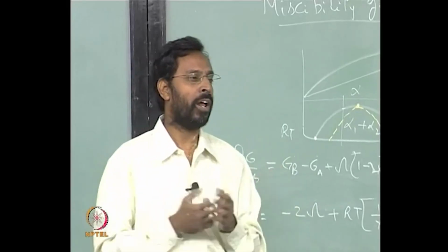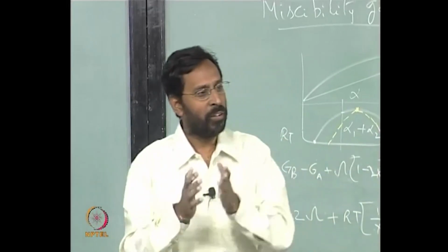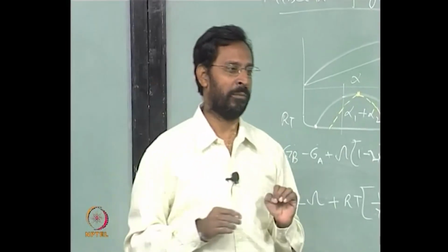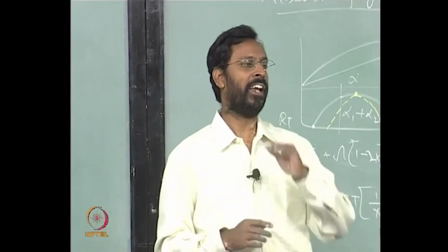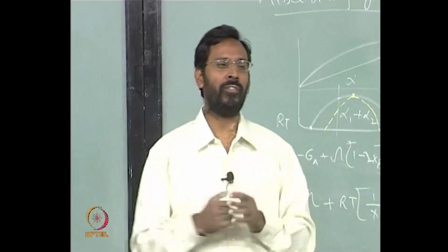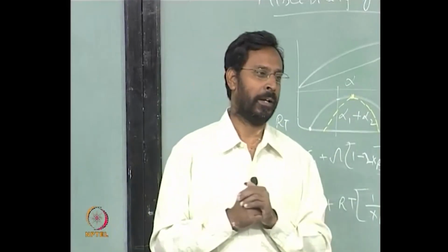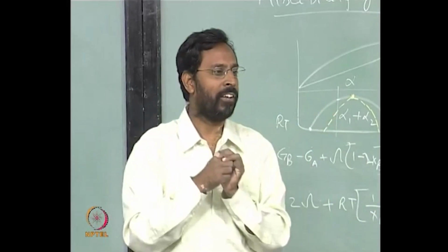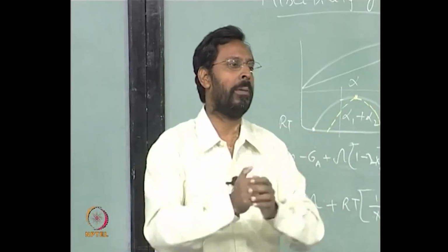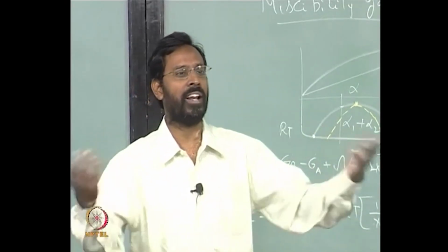For example, iron boron, if you look at it, 20 of boron and 80 of iron is the one where you actually see this is happening, and that is the reason why if you look at iron boron phase diagram, you have a deep eutectic at 80-20. Same thing palladium phosphorus, you go and see palladium phosphorus phase diagram at 80-20 you have a deep eutectic. That means for such a configuration the liquid will have a high density and such a liquid gets stabilized, and once the liquid is stabilized, glass is stabilized.